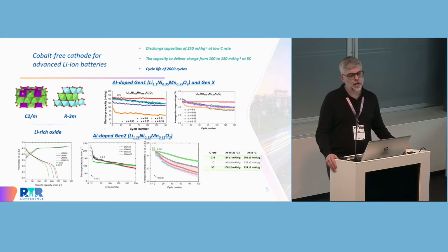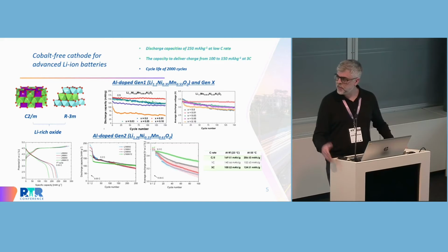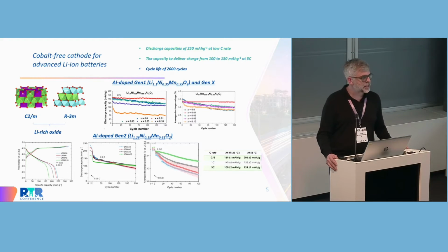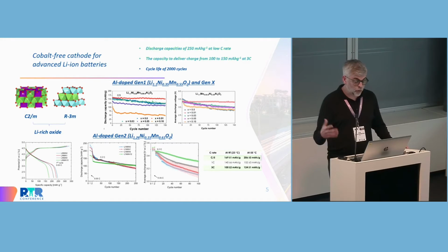For the cobalt-free ones, the new oxide material that we are working on is a lithium-rich, which is a composite of monoclinic and rhombohedral phases. This is not as well-known a material as NMCs or spinels, but in my personal opinion they are very interesting materials, so I'm trying to push them forward in other proposals. We have been working on doping scenarios, and we have managed to improve the stability by aluminum doping quite nicely.